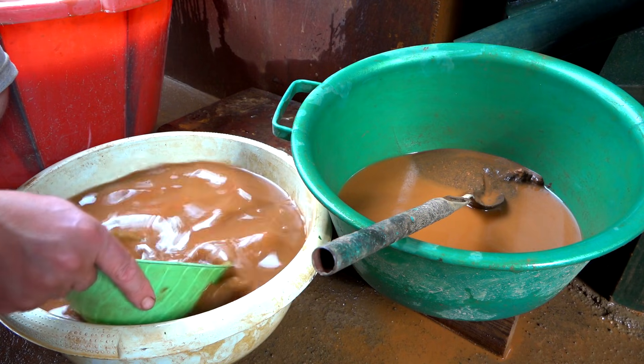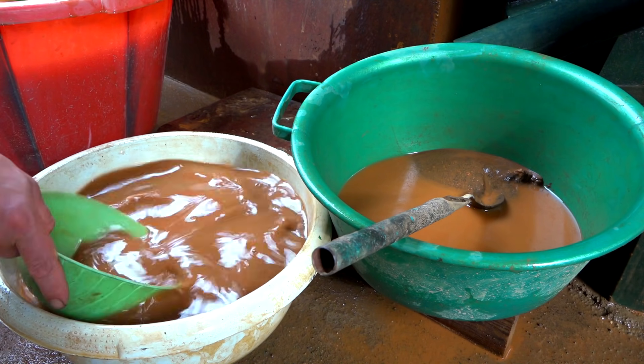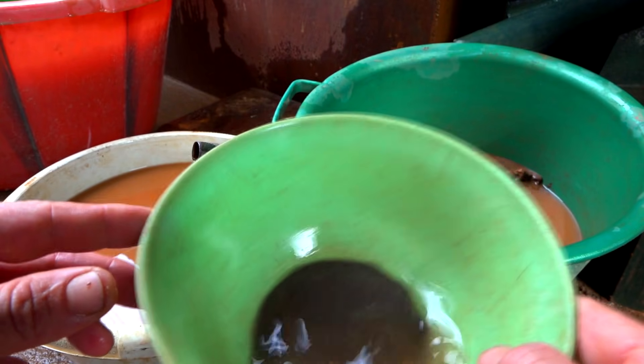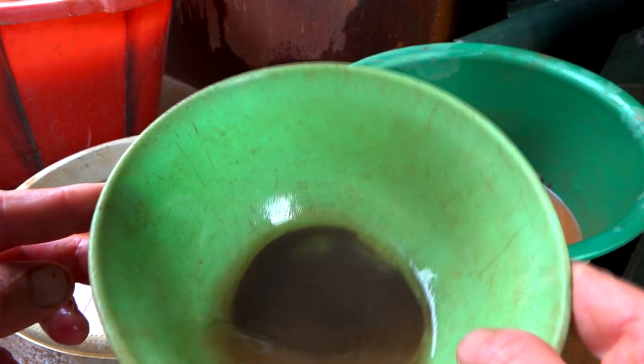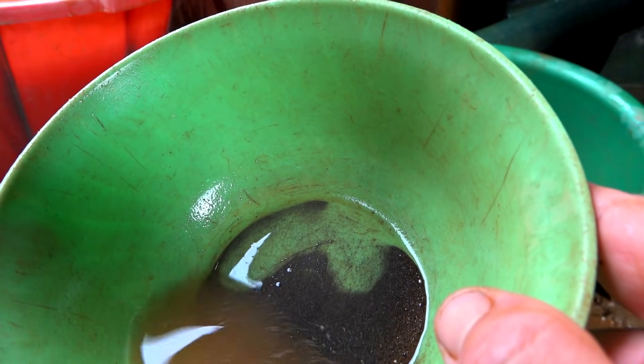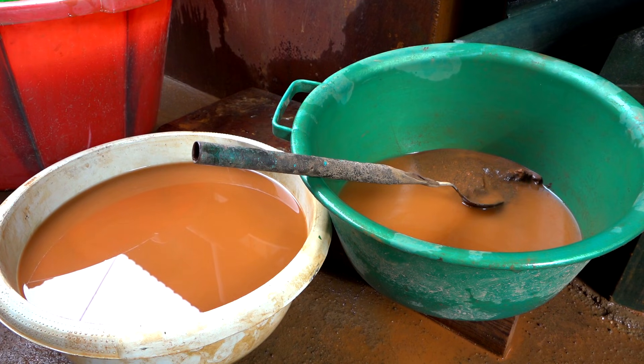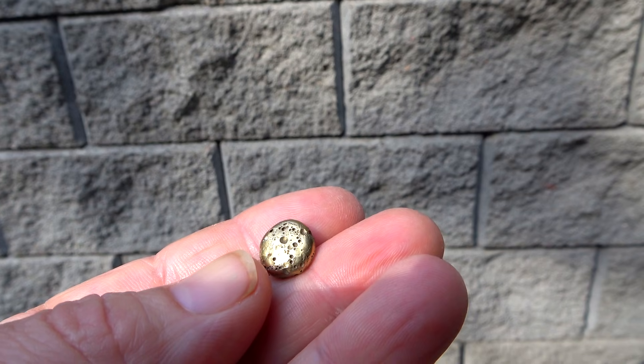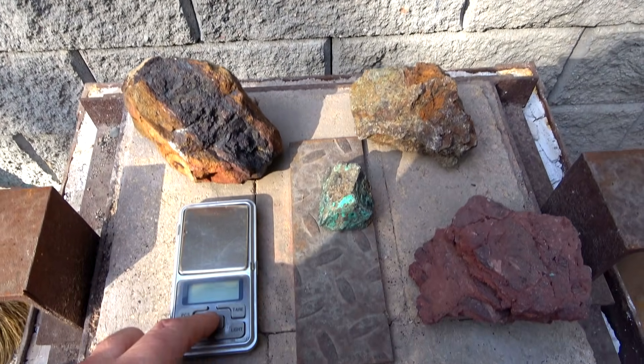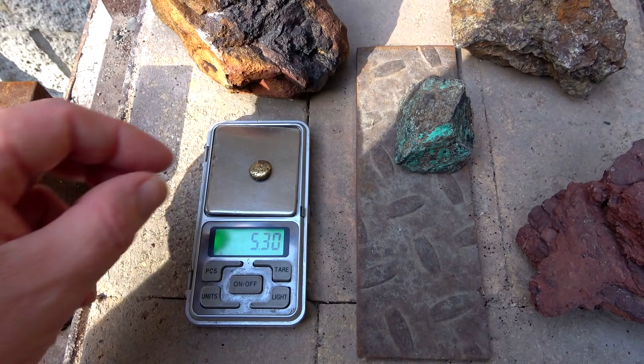This time there was almost no large gold visible to the eye. I could put 10 or even 50 grams of real gold in for a beautiful picture, but I don't want to deceive you. I have a lot of gold, but my goal is to show you how it really works. These stones do contain gold — I have already processed many tons of them. Gold in such ores is mostly elusive and invisible to the human eye since the particles are micron-sized. This rust-colored water is literally filled with suspended gold particles. I managed to extract a small piece of gold from 300 kilograms of these stones using flotation to extract gold microparticles from the concentrate, then fused the flotation concentrate with lead, and extracted this piece of gold by cupellation.